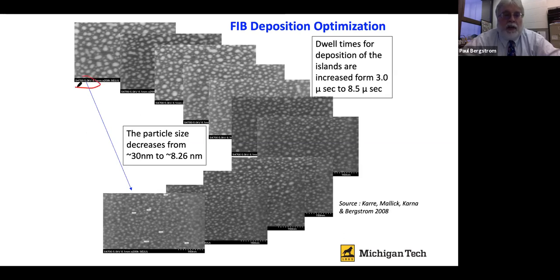We started out getting about a 30 nanometer nominal size of quantum dots. How can we work our process and control our process so that we can get down to average quantum dot sizes in arrays that are small enough that they're going to work? And we did actually do this. Using some image analysis software, we were able to determine that our nominal size for the quantum dots in this process condition was about 8.26 nanometers. And it was very consistent from process to process, meaning we could get to a quantum confined quantum dot at room temperature in this particular material, which was tungsten, to allow us to build these devices.